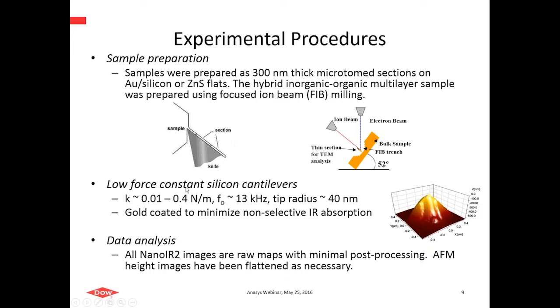Since we're relying on the photothermal effect, that is the kicking or ringing of the cantilever, it helps if the cantilever spring is fairly soft and weak, and so these are low spring constant cantilevers for those of you who are practiced in the AFM methodology. They're also gold coated to minimize non-selective infrared absorption. They're metal coated probes. And on the lower right-hand side here is a reconstructed image of one of these probes with about a 40 nanometer radius at the outer apex, just to give you an idea of its shape. One of the things we really enjoy about the nano-IR capability, AFM-IR, is that the raw image maps are rendered without really any need to do any post-processing, and they're fairly straightforward to interpret. The height imaging that I'll show you may have been flattened to remove artifacts or leveling.